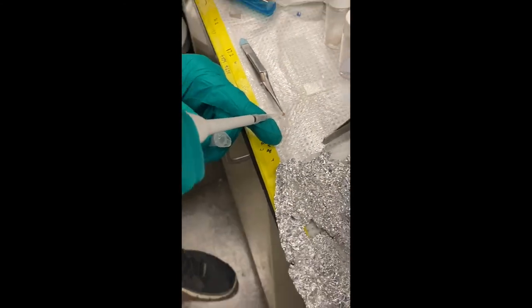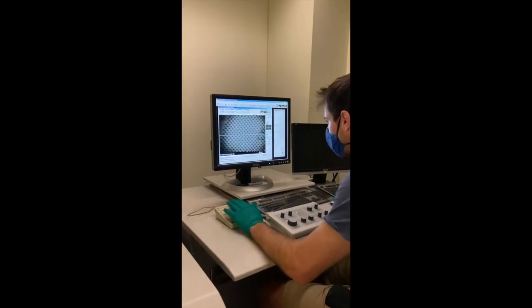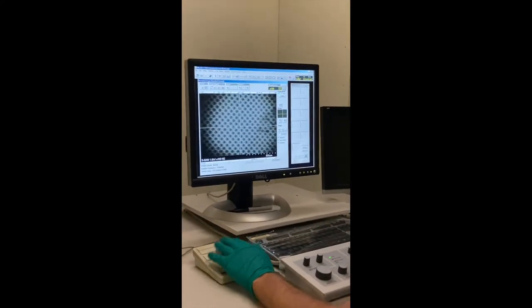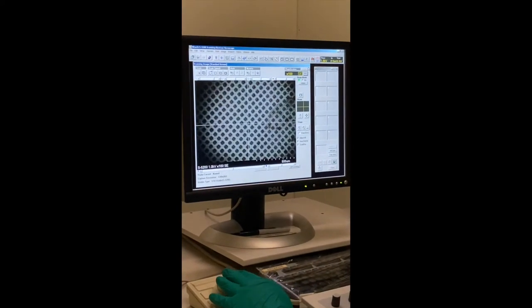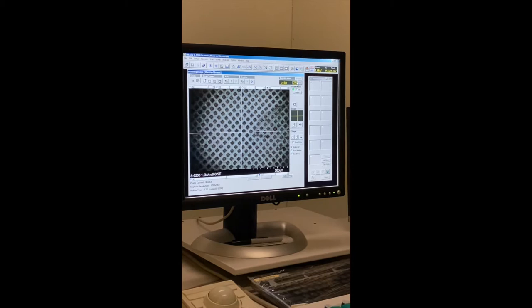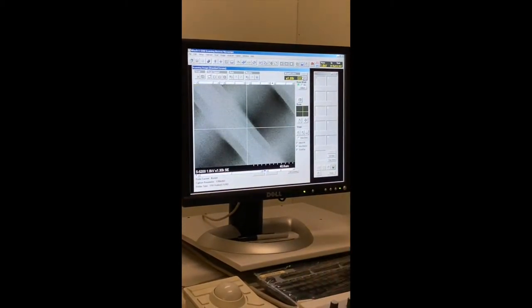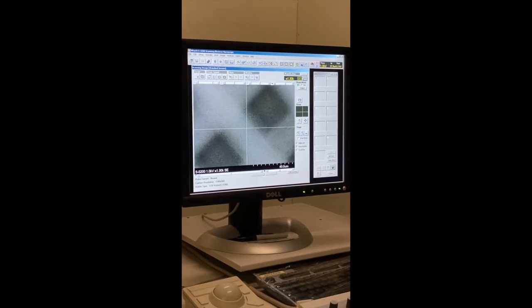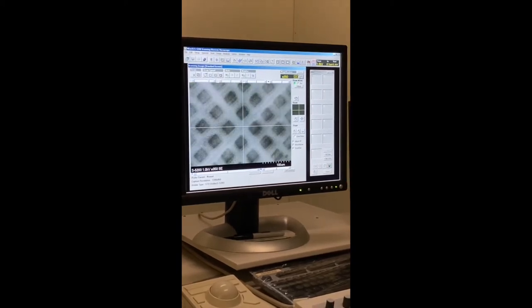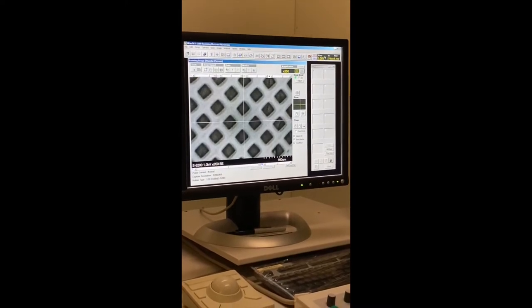The last piece of instrumentation I want to cover is the grid. As mentioned previously, the grid is what allows our sample to interface with the TEM. A grid consists of a copper grid of a certain mesh size coated with a thin layer of carbon, and sometimes a thicker layer of Formvar, which is a structurally supportive polymer. Our sample will sit on top of the carbon layer and hopefully in between the supporting structure of the grid. Then, when we look at our sample through the microscope, the probing electrons have very little interaction with the carbon layer, greatly reducing the background of our image.